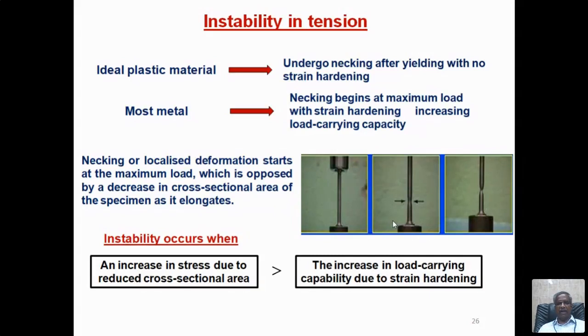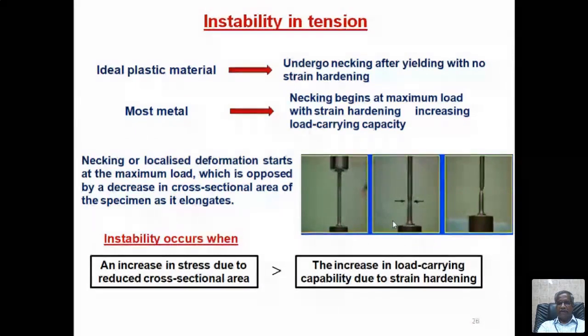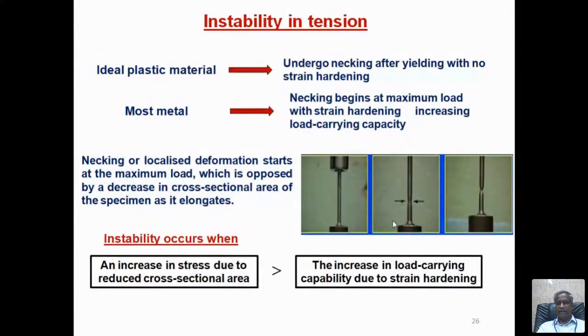So when will instability occur? Increase in stress due to reduced cross-sectional area, because when necking starts, the reduction in cross-sectional area occurs. You see the first specimen, the second specimen, there is a reduction in cross-sectional area. But the load is the same load you are maintaining. Whatever load you are applying initially, you are not reducing the load. So the load is higher, but the area is less. Because of that, stress is increasing. So that is called the increase in stress due to reduced cross-sectional area. That should be compared with the increase in load carrying capability due to strain hardening. Because of this, a work hardening is taking place. The deformation is what?